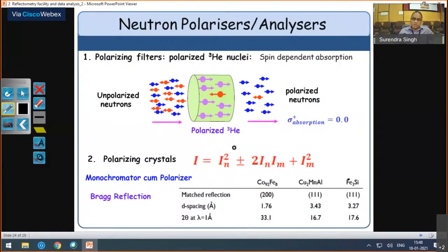This is like helium-3, which satisfies the Bragg condition. So if you have a large wavelength, you cannot use it. It's only used for monochromatic wavelength, because every time you have to change the angle of incidence to satisfy the Bragg conditions to get the polarized beam. So one wavelength gets reflected at one angle of scattering, another at a different angle. So for time of flight or pulse sources, this cannot be used.